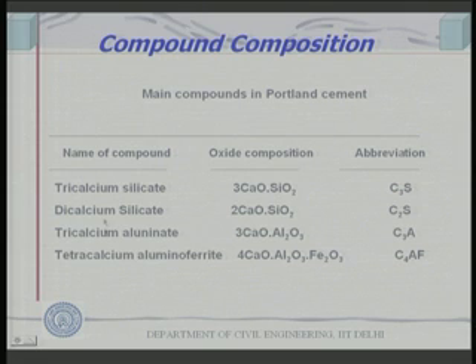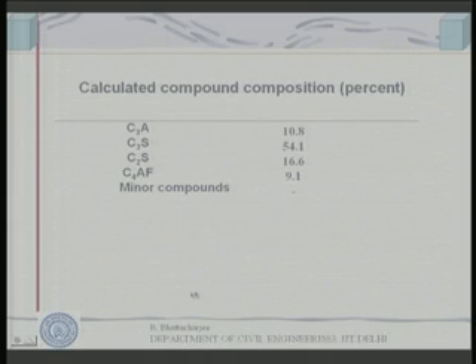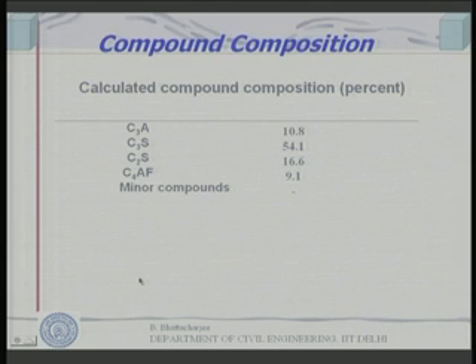This has been repeated, so that this is clearly remembered, because that is the terminology one uses again and again in the context of concrete and cement. Right. Now, if I calculate the compound composition based on the Bogue formula that we mentioned, we find that C3A comes out to be about 10.8%. C3S comes out to be 54.1, C2S comes out to be 16.6, and C4AF comes out to be 9.1%,